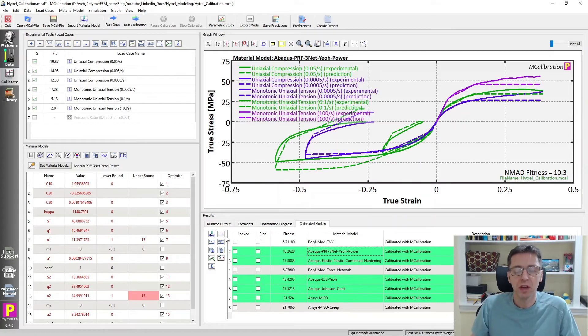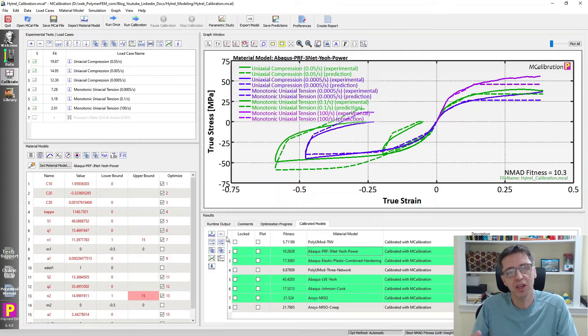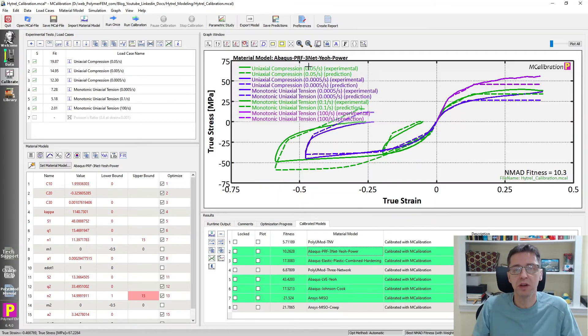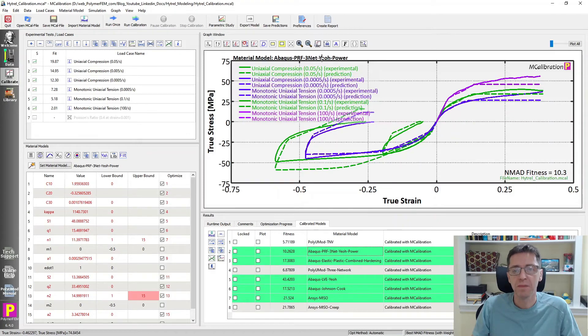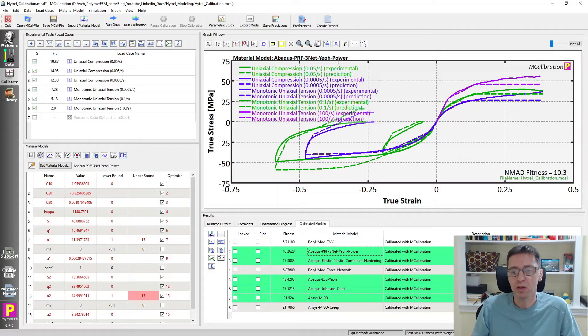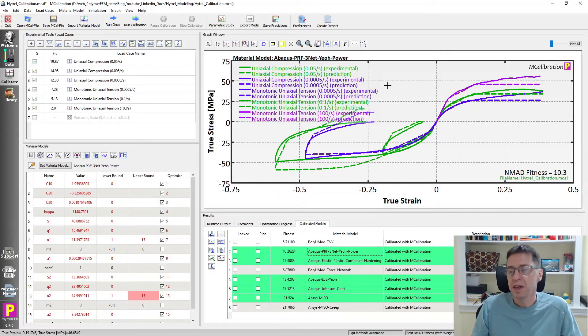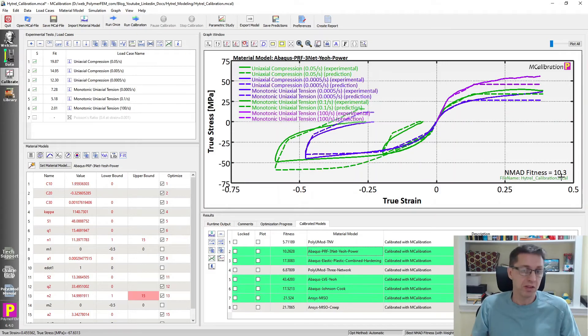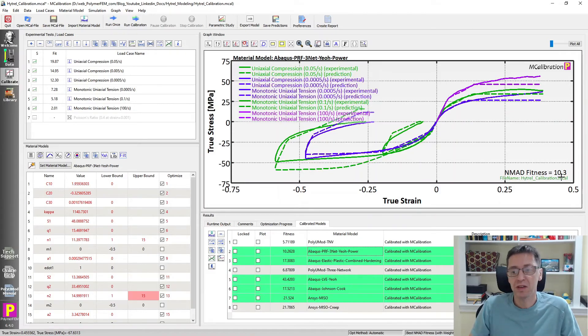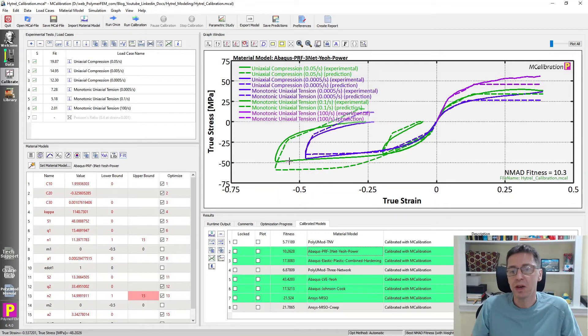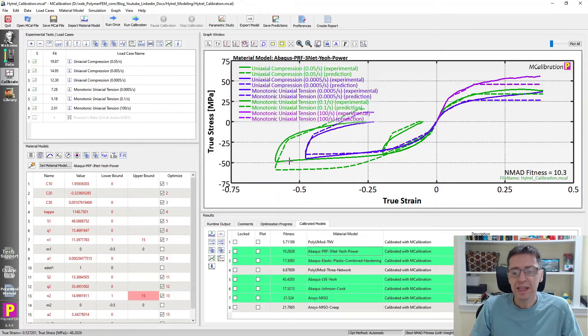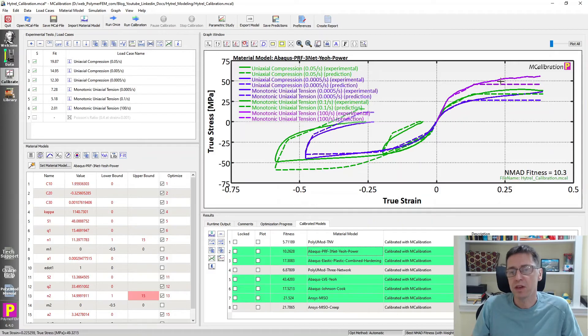In this case, I use my favorite representation of the PRF model for this class of material. It's a three network representation with dual hyperelasticity and power law strain dependence of the viscoplastic flow. That usually works pretty well. In this case, the error is better than the plasticity models, as one would expect. It's down to 10%, the loading, the unloading. Most aspects are reasonably well predicted.